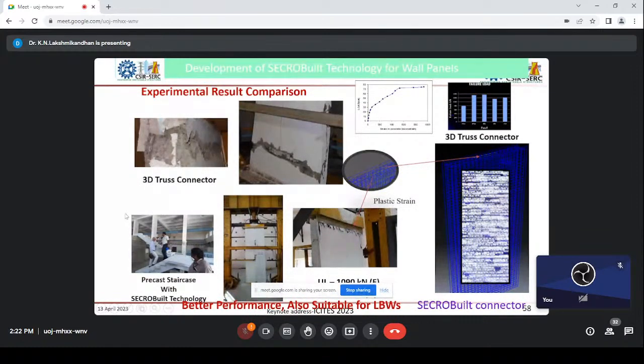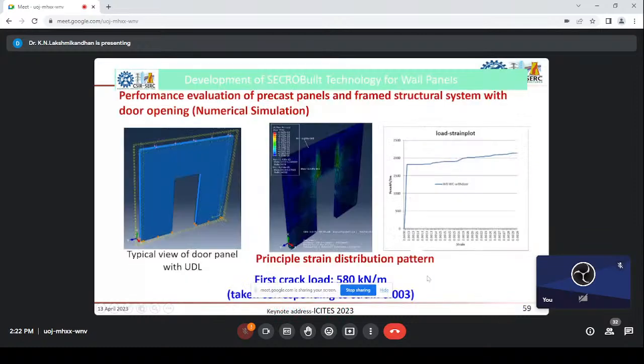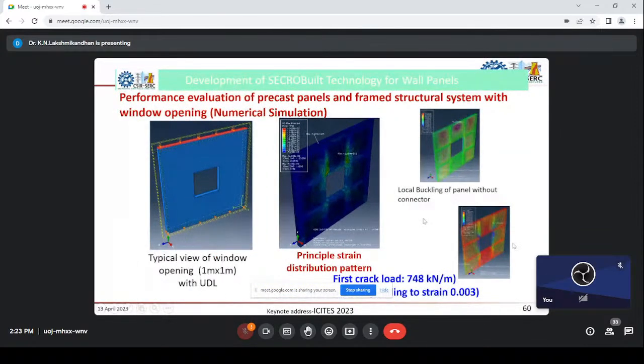In a similar way, we develop precast staircases using the ferrocement concept, and each one is an individual element, which is just positioned at the location and can be integrated together within a few hours. This is a typical analysis we carried out for the EPS infilled salvage panels with the door opening, and similarly this is for the window opening. In all the cases, the failure is very localized. Even though the load is applied here, you can see the load is distributed uniformly. As a result, the entire system is acting together, and no isolated concentrated stresses are seen in this structure.